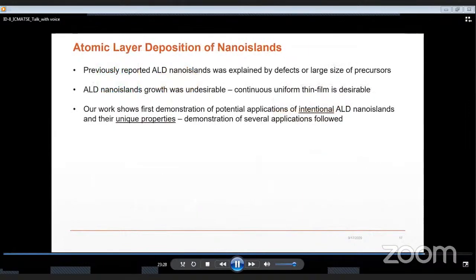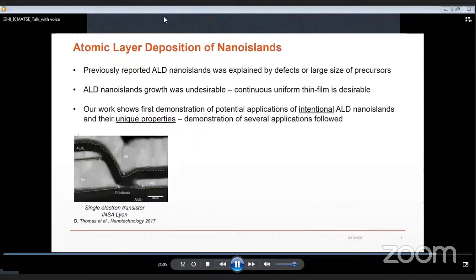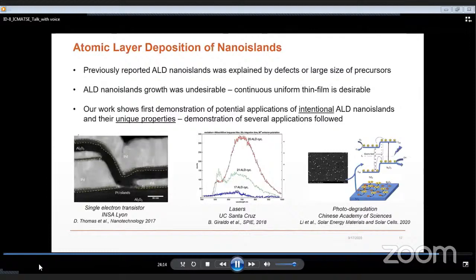I would like to mention here that previous to my work, the ALD-based nanoislands were considered an undesired result and were explained by having defects on the surface of the substrate or the large size of the precursors. So researchers were trying to get rid of these islands and get continuous thin films instead. My work on the intentional growth of nanoislands using the ALD tool on different substrate terminations, and then characterizing them and showing that they actually have unique properties and showing their potential application in memory and solar cells, was the first demonstration. Other international groups followed and used the ALD nanoislands in other applications, including single electron transistors, lasers, and photodegradation applications.